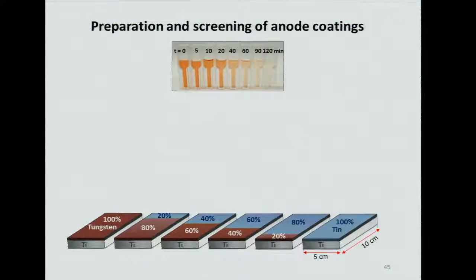As you can guess from its name, phenol red has red color. In the picture above, you see phenol red in the samples taken from the reactor at different times during the experiments, filled in the cuvettes. And as you can see, the phenol red was almost completely removed from the system after about 120 minutes.